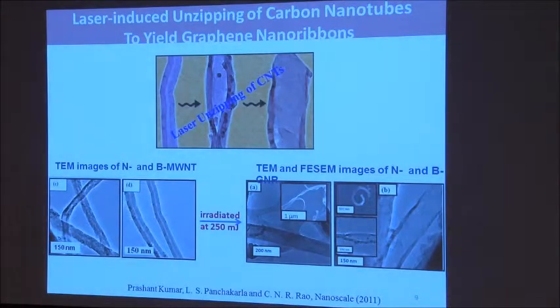One also made important materials like graphene nanoribbons. If you take graphene, which is a sheet, and cut it into a rectangular piece, it becomes a ribbon. One way of making it is by oxidizing carbon nanotubes. The method we used is to use a laser to unzip the nanotube and make a strip, which is a very nice way of making very clean nanoribbons. All this has happened in the last few years.